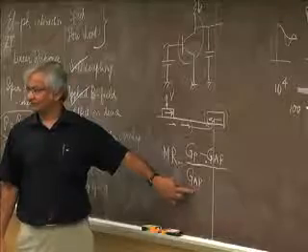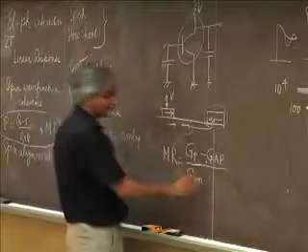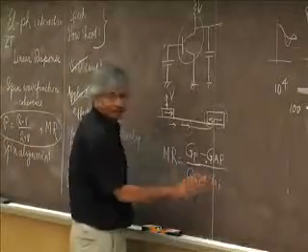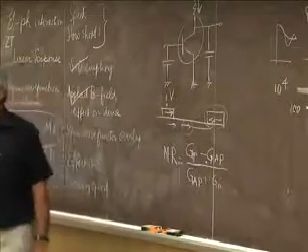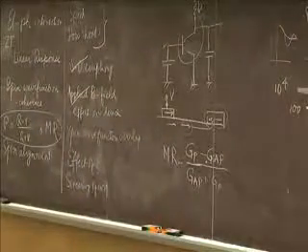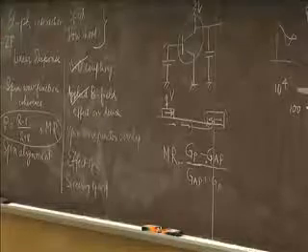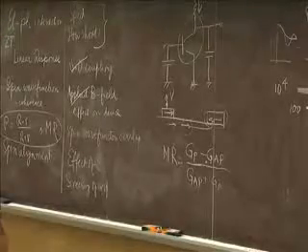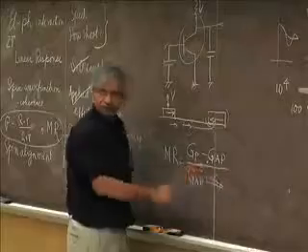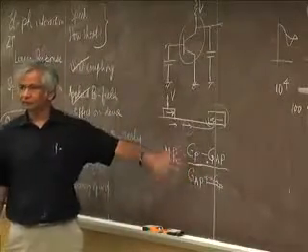So you could actually get 500% magnetoresistance, for example. On the other hand, if you had defined it with the sum here, then of course you would never be more than 100%. But what you see in the literature, you have reports of 500% magnetoresistance. That's because the definition is like this, which could well exceed 1.